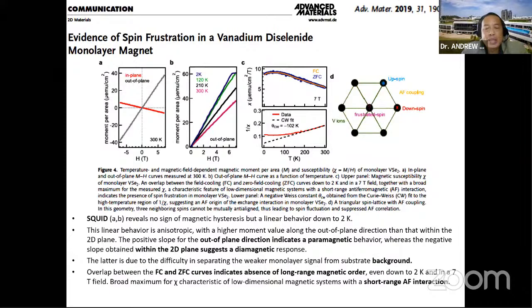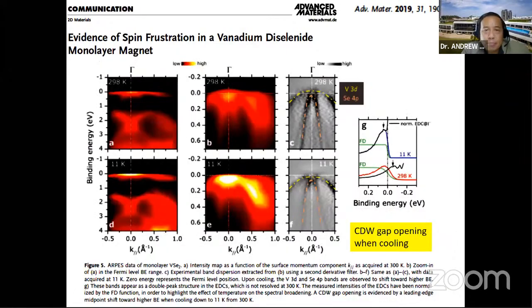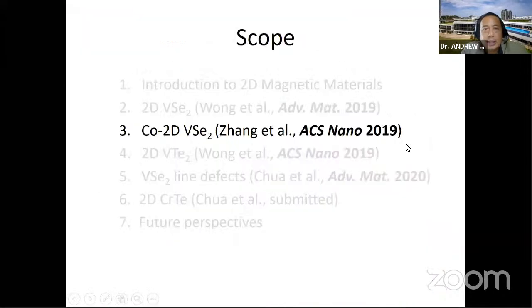It needs some extrinsic perturbation in order to make it magnetic. And we think that is the reason for the magnetism reported in some previous work. So this is some ARPES results on the electronic structure that showed a small CDW gap opening when cooling. Right, so that was our conclusion, that vanadium diselenide is a frustrated magnet.